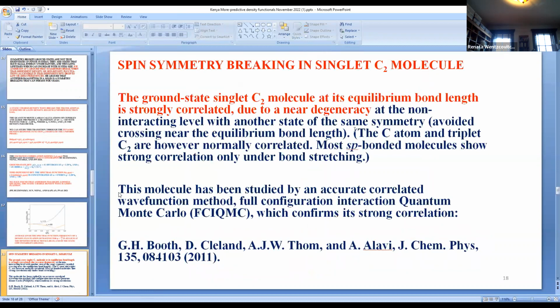Now I'll give you another example, more closely related to the SCAN functional: spin symmetry breaking in the singlet carbon dimer, the C2 molecule. Most sp-bonded molecules are normally correlated and well described by density functionals without any symmetry breaking. But the singlet, or spin-zero state, of the carbon dimer is an unusual case—it is sp-bonded, but strongly correlated. That's discussed in this paper by Alavi and collaborators from 2011.